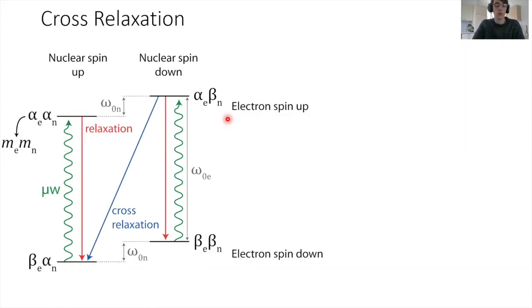So why is that? I'm going to show this now for the case of a 4-level system. This is a bit of a simplification because in a metal these are all bands, but it suffices to explain the effect. On the left, our nuclear spins are up, and on the right, our nuclear spins are down, and at the bottom, our electron spins are down, at the top, our electron spins are up. So we start off at thermal equilibrium with an excess population of these lower energy states.